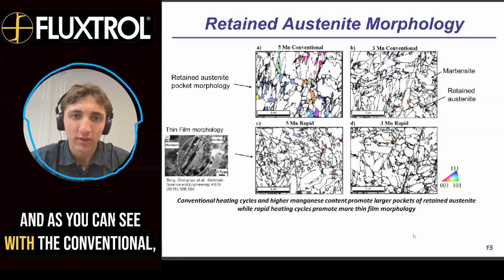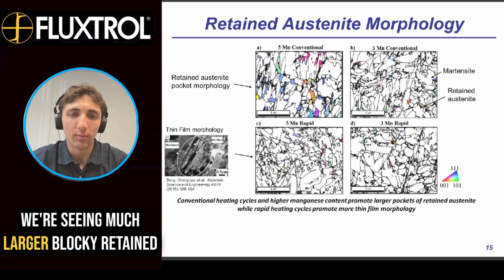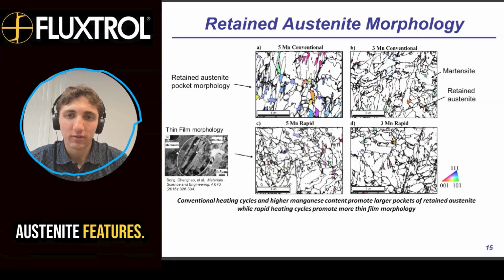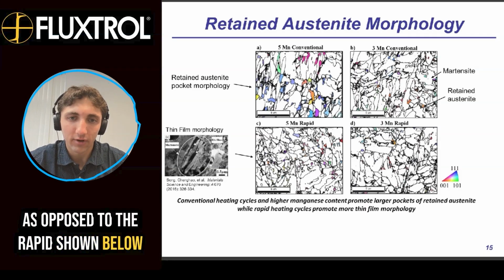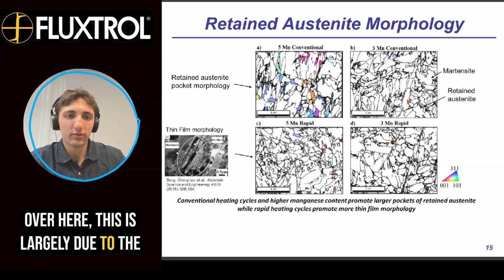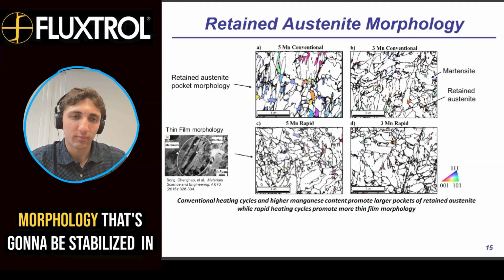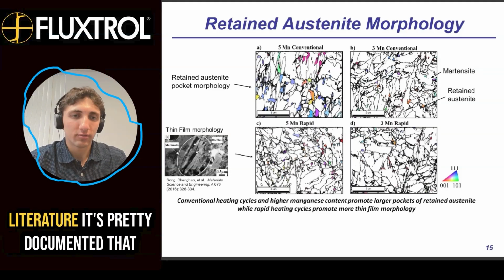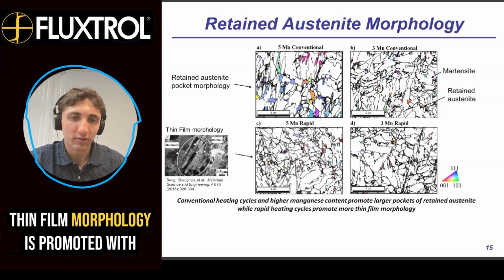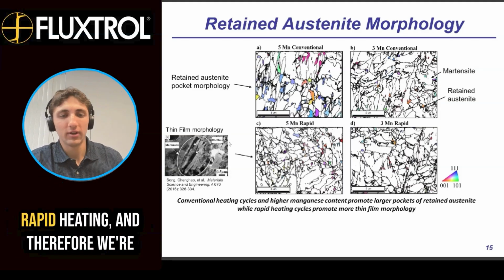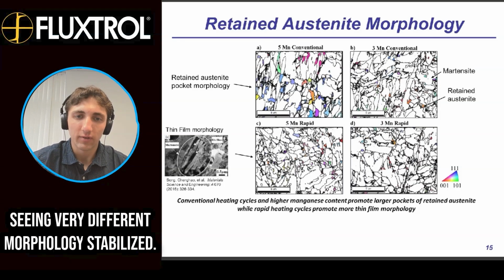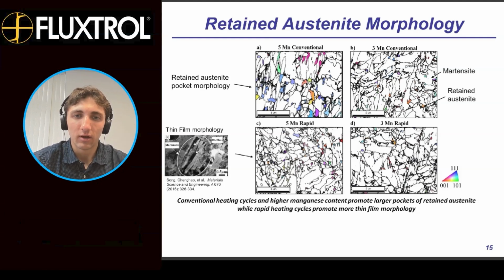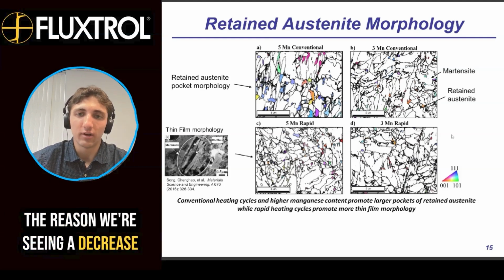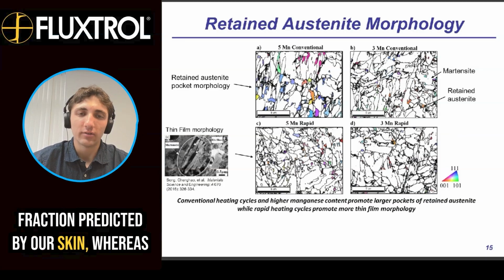And as you can see with the conventional, we're seeing much larger blocky retained austenite features as opposed to the rapid shown below over here. This is largely due to the difference in the retained austenite morphology that's going to be stabilized. In literature, it's pretty well documented that thin film morphology is promoted with rapid heating, and therefore we're seeing very different morphology stabilized.